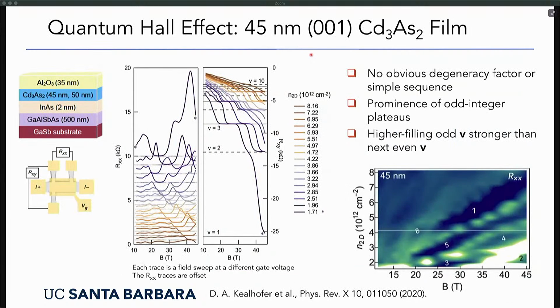The first experiment is again looking at the quantum Hall effect, this time in a gated Hall bar structure where we modulate the carrier density in the cadmium arsenide surface states. The results are shown here. Each of the traces in this graph in the middle of the slide corresponds to a different gate voltage, and therefore a different carrier density.